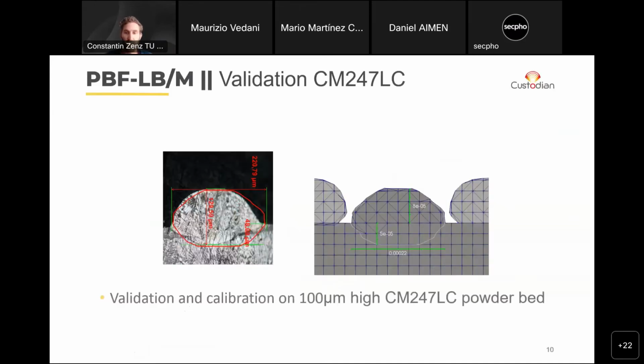So let's at first look at the results for the first material, the CM247LC. Here you can see a comparison of an experiment. This is just a single track of melting with a powder. So a powder layer and then just one single line of melting powder and therefore welding it to the substrate. We see some measurements from the experiment, and then on the right, you can see the corresponding simulation result. This was done to validate that the simulation is reproducing the same weld bead geometries as the experiment. And we were confident the results were satisfactory. So we used the simulation to then try out different beam shapes and find an optimum in terms of weld bead shape and cooling rates.